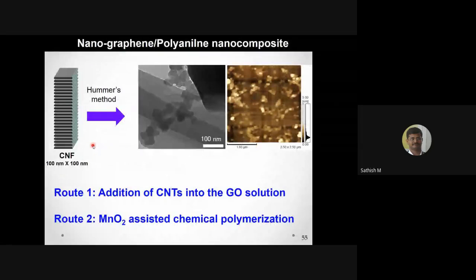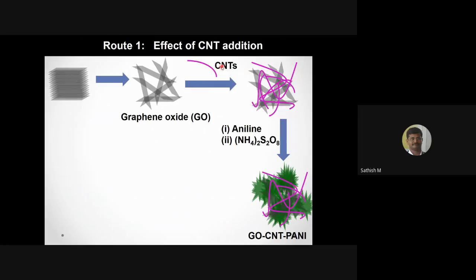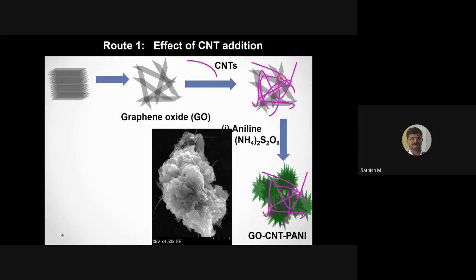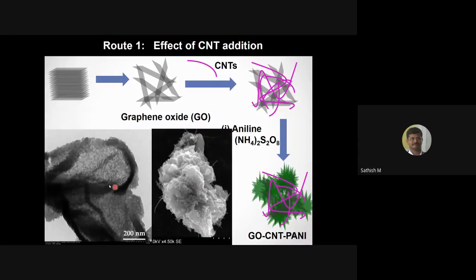To avoid this, what we have done is we added some carbon nanotubes, small carbon nanofibers like this. So the carbon nanotubes will mix up, and when you add aniline, the aniline gets polymerized. We thought that there would be space to reach the graphene surface. But unfortunately, again we ended up with some very thick polymerization, because this polymerization is not a controllable process. You can control it by varying the aniline, but still you cannot control the thickness of polymerization.